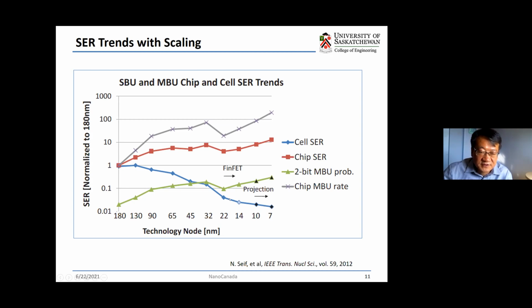Eventually, for FinFET, you can see that when we use the FinFET technology, this becomes smaller because it has a thinner diffusion in the drain and the source layer. However, the problem is that the 2-bit and multi-bit upset rate is increased. The reason is also very simple, because the cell size is getting smaller, right? When we put the SRAM cells together, one ion hit can easily generate a multi-bit upset, right? And so that's why the 2-bit multi-bit upset probability increases.